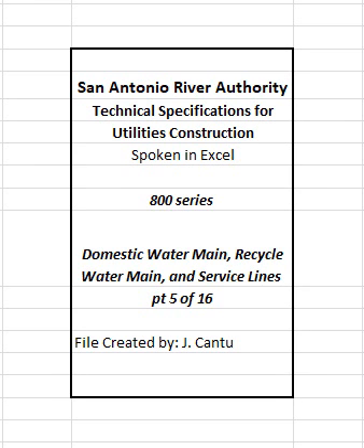Mechanical. The polyethylene film shall have a tensile strength, per latest ASTM D882 test, of 6,300 psi minimum. The film shall have an elongation of not less than 100% of the test strip minimum per latest ASTM D882 test. The film shall have an impact resistance of 800 grams minimum per ASTM D1709 method B. The film shall have a propagation tear resistance of 250 gf minimum in machine and transverse direction, ASTM D1922. Dielectric.